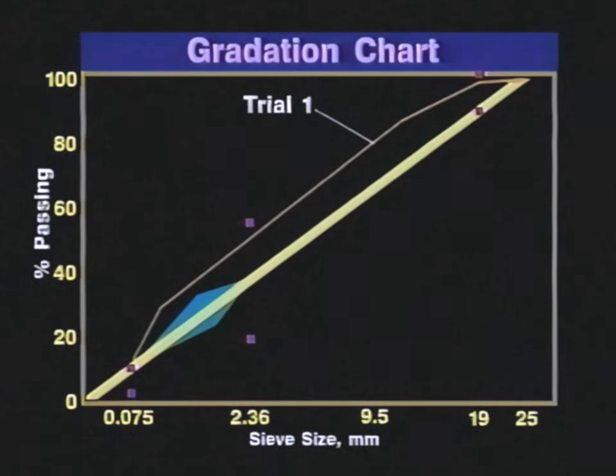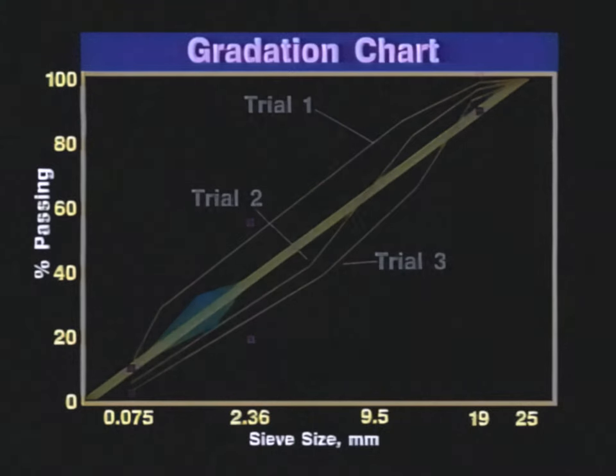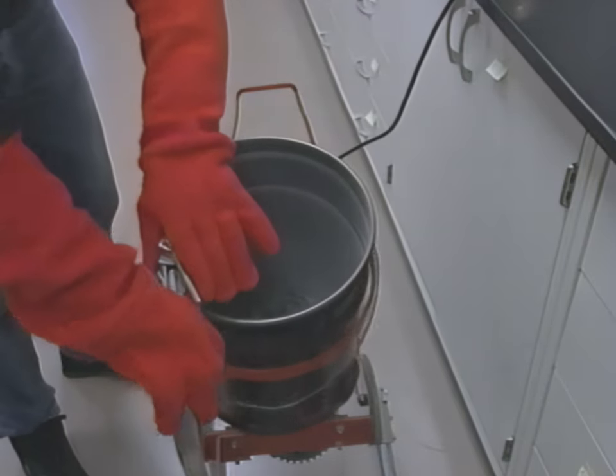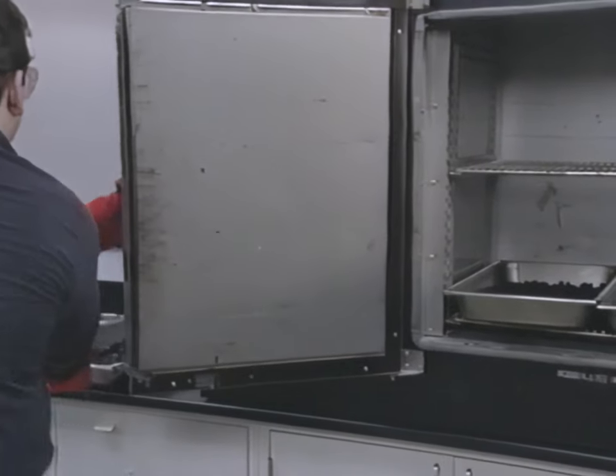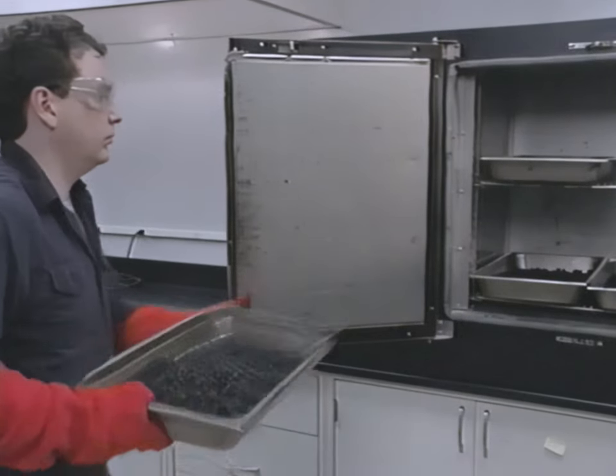The next step in designing a SuperPave mix is determining the optimum aggregate structure. The aggregate sources are evaluated to develop three or more trial blends that meet the gradation requirements. Aggregate properties for the blends are then calculated. The appropriate PG asphalt binder is then mixed with the aggregate, and the mix is aged in an oven to simulate the aging that occurs during the construction process. The trial blends are evaluated by compacting the specimens and determining their volumetric properties.